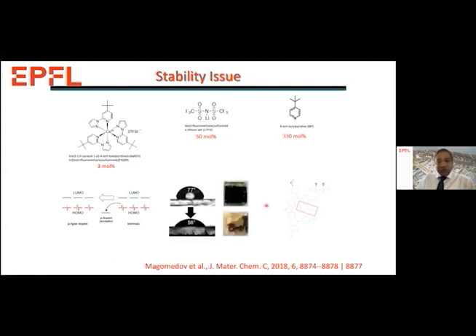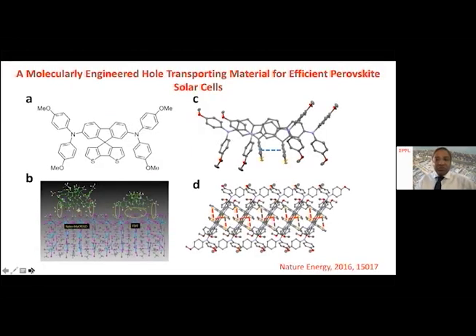And therefore, you can also see, because of these ionic compound additives, that without any dopants, the contact angle measurement shows 77 degrees. With these ionic dopants, the contact angle is decreasing. That means it's becoming hydrophilic. So this provokes instability in the material. So can we improve the stability?